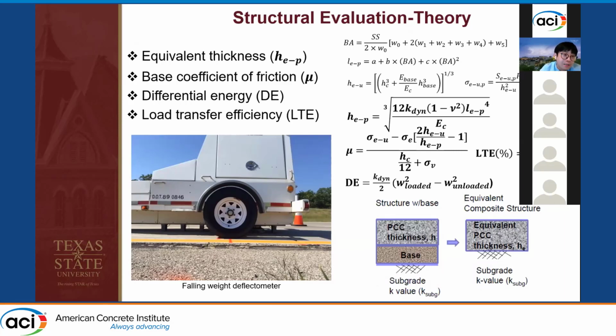So we look at 4 major parameters for the concrete pavement structures. We developed some theories to evaluate base erosion using FWD results. Those 4 parameters were: equivalent thickness, which considers both base and concrete slab, and also considers the bonding between those 2 layers. We also look at the base coefficient of friction. As I mentioned, we had a theory that calculates those coefficients. We also calculate differential energy using the pavement ME equations. And we also look at load transfer efficiencies. There are lots of theories and equations behind this. I'm not going to go over them today. If you are interested, you can find those equations in our TR paper, which I will list at the end of the presentation.